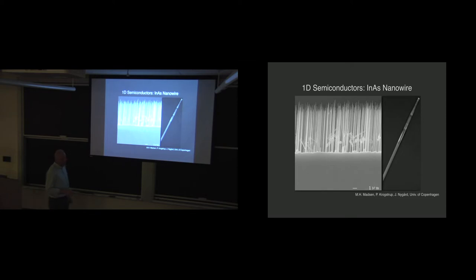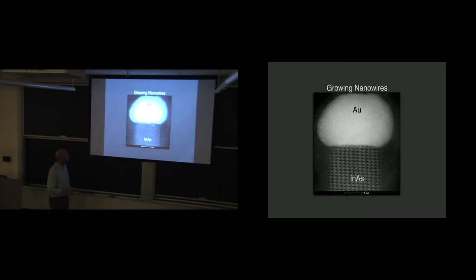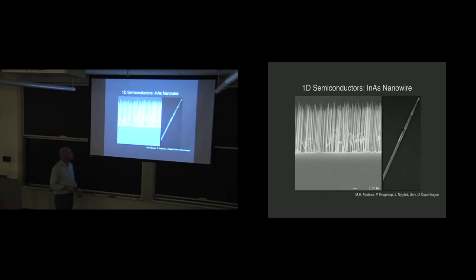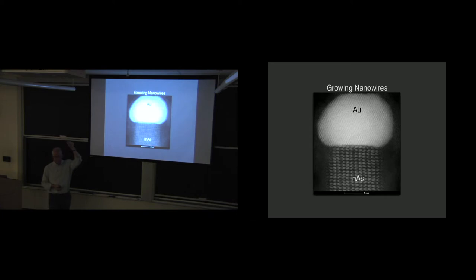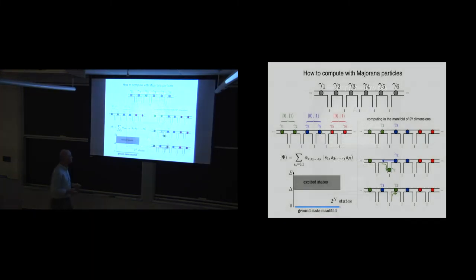You put a gold ball down on the surface of the wire. The gold ball catalyzes the crystallization. I can show you even a zoom in. Here's the gold ball catalyzing the crystallization of indium arsenide, and it just pushes the ball up into the air, rising up on this catalysis underneath it until you have this long one-dimensional wire whose diameter is set by the size of the ball. So if you want to learn how to do that, go to Javad and he'll show you. But it produces this one-dimensional, essentially perfect crystal of indium arsenide or indium antimonide or silicon or different materials that can grow, catalyzed by the gold on top.